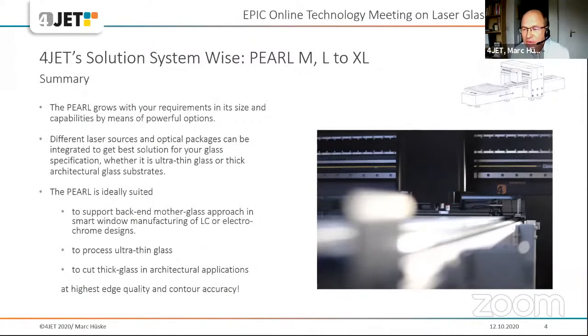The solutions that we provide are called pearls, according to the pearl cut technology. And you can see on the upper right, it's basically a system that can be scaled in size based on a table where the glass is fixed to. And then the table moves underneath the laser beam, and the stage moves the laser head across the surface of the glass. And by using both motions synchronously, you can introduce any cut line into the glass. We can integrate into those systems different types of laser sources and different types of filamenting optics. We have heard about a few Bessel beams and special optics we are using from Coherent, for instance. We are open. We, of course, rely on products, and products need to be standardized to some extent. So we try to keep our suppliers in a small number.